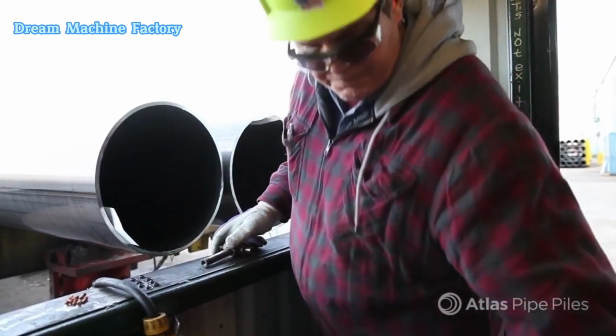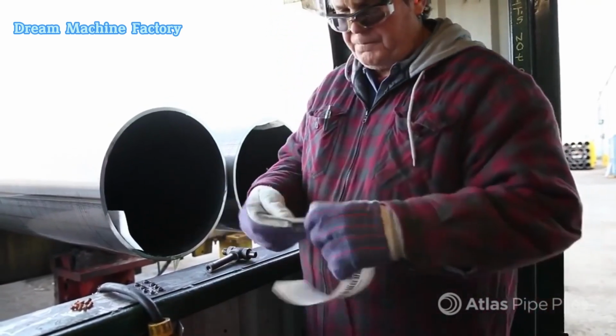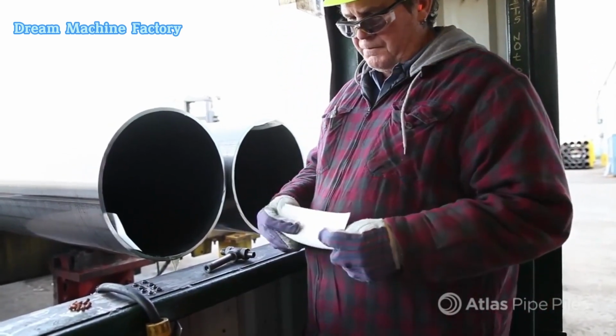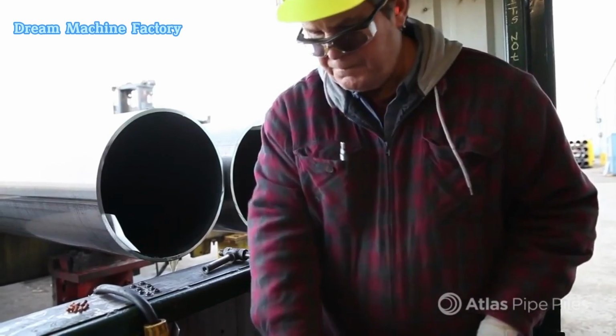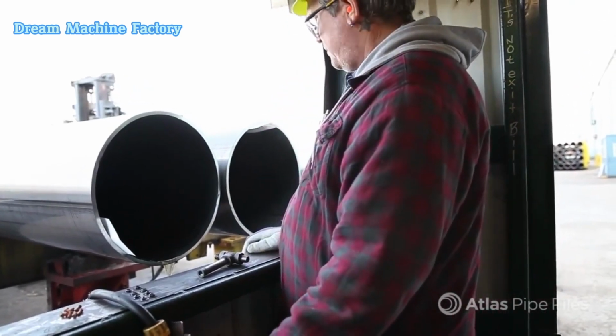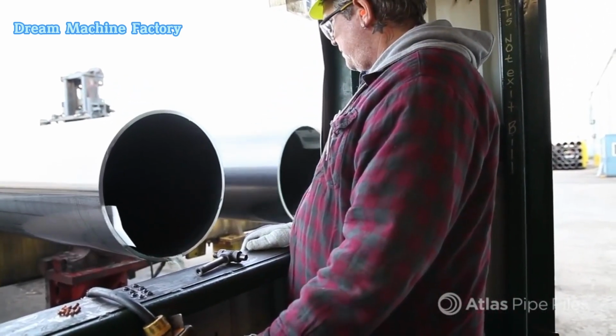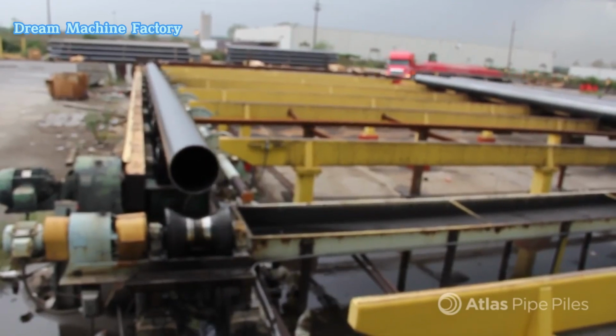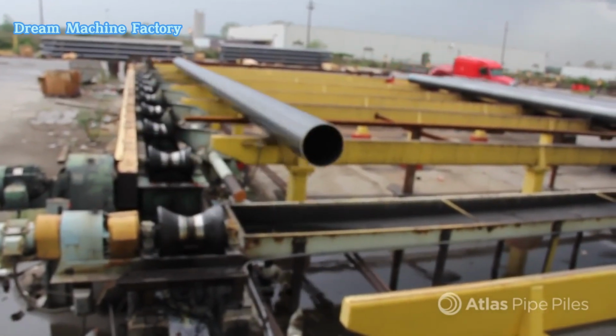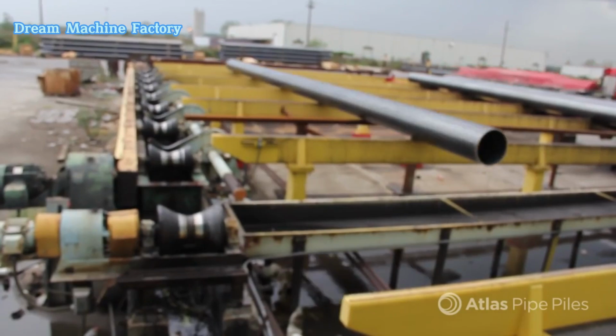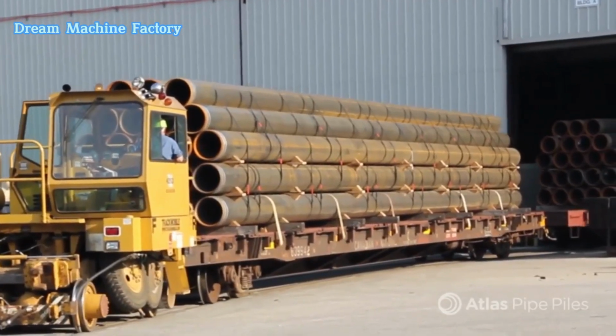Destructive testing further verifies the product's performance. The cone test uses a hydraulic press to expand the pipe until it fails or achieves a predetermined expansion without compromising the weld. The flattening test assesses the ductility of the steel by flattening a sample at different angles to the force.